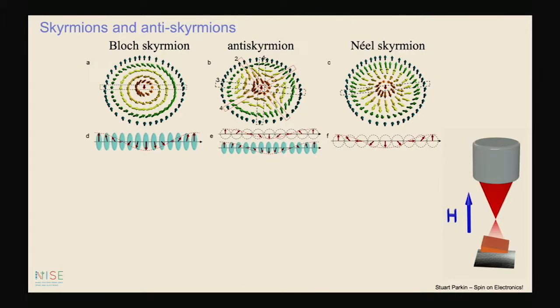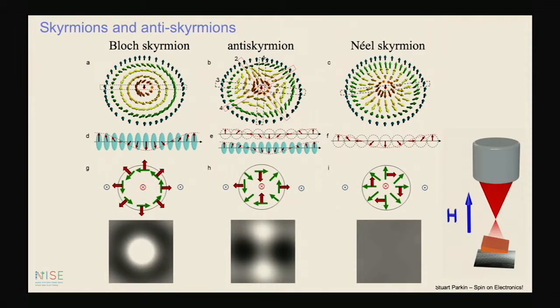So in our aberration-corrected microscope in Halle, we essentially pass 300,000 volt electrons through a very thin sliver of the material. We form this from the bulk material. And as the electrons cross this material, the in-plane magnetic fields or magnetization cause motion of the electrons to the left or to the right. And this leads to distinct patterns for each of these objects. So this is what we can calculate the patterns to be.